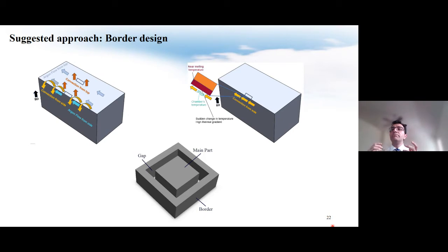In another word, the input energy delivered to the area near the surface is lower than the middle region, as is shown in this picture as well. And that is why we see more cracks, unmelted powder, irregular melt pools, and maybe refined grains. As a potential solution, we decided to consider a border with an offset from the main part during the fabrication for this study. Our aim was to control the convection heat transfer that occurs near the surface area.